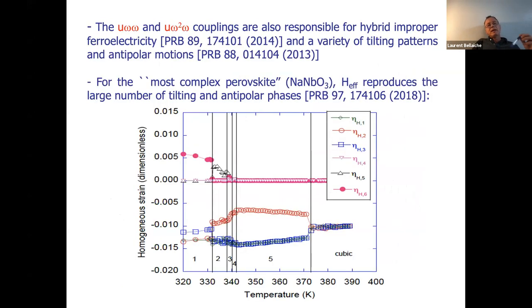And these couplings are also responsible for a lot of different physics. For example, they are responsible for what is called hybrid improper ferroelectricity. You put two PNMA systems together that do not have a polarization separately. When you put them together, they have a polarization. This is due to this coupling.